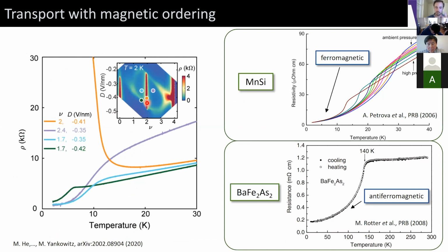And if I just go to other systems that have been measured in the past with either ferromagnetic or antiferromagnetic ordering, it turns out that there's actually some qualitative similarity in the way that transport looks below the Curie or Néel ordering temperatures. So for example, in manganese silicon, there's a ferromagnetic transition that's tunable with pressure, but you see this linear in T temperature dependence, and then this abrupt drop below the Curie temperature, and then the resistance is much smaller at base temperature. Similarly, in barium iron arsenide, there's an antiferromagnetic transition below a Néel ordering temperature of about 140 Kelvin, and again, you also see this abrupt drop in resistivity.